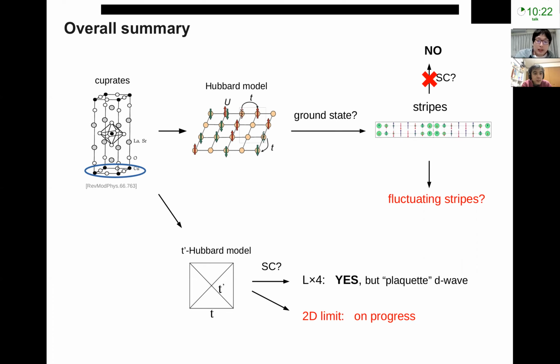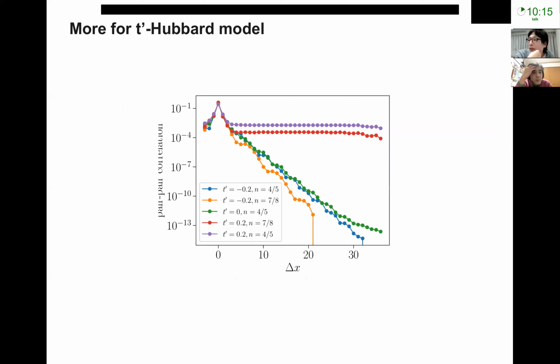I should also show you some unpublished work - this is not a definite conclusion, but here we consider T-prime on a larger cylinder, both positive and negative T-prime, and we found it's pretty easy to find a stable superconducting state for positive T-prime, but it's pretty difficult to get a good superconducting state with negative T-prime. This is also similar to what was observed in the t-J model.